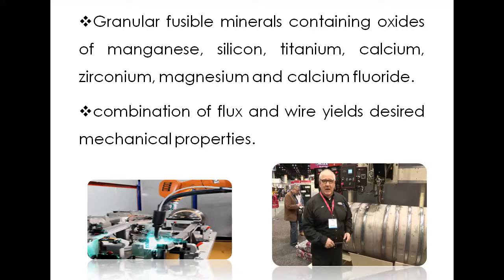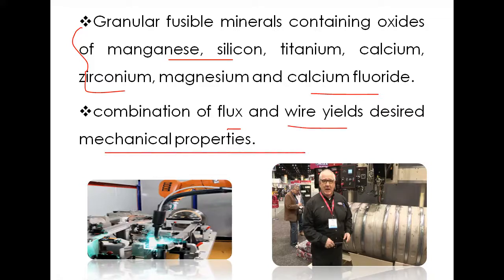Many minerals are already present in the granular flux medium: oxides of manganese, silicon, titanium, calcium, zirconium, magnesium, and calcium fluoride. These are the alloying elements present in the granular flux medium. The combination of flux and wire decides the mechanical properties. To give good mechanical properties, the submerged arc welding process is suitable for joining thick metals, with deep penetration, as well as improved mechanical properties of the joints.